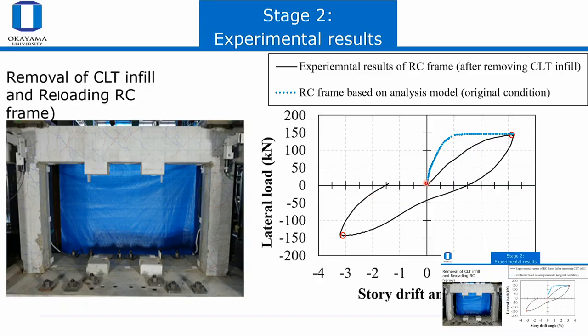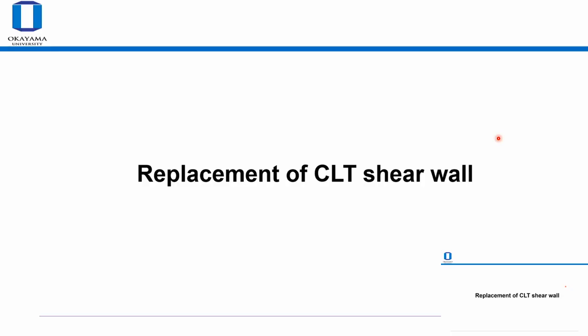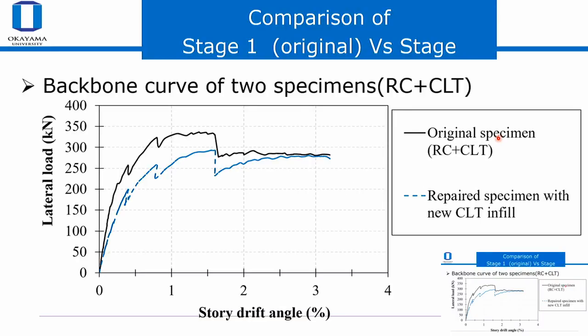By using the analytical model, it should go like this, the blue line. But because the RC frame is already damaged and has some cracks, the initial stiffness degraded, but the maximum strength, since it depends on the repetitiveness, still doesn't change much. And then we thought that's okay. We haven't repaired the RC frame. And then we put a new CLT wall in and tested again.